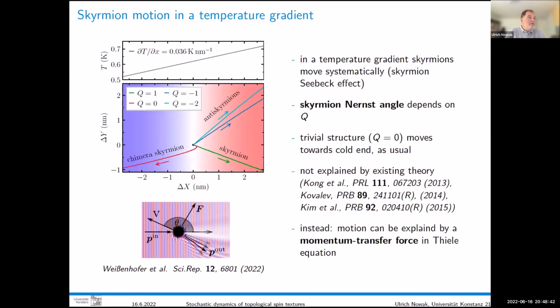The last slide I wanted to show regarding results is now what happens in a temperature gradient. So I showed already, okay, at finite temperatures, skyrmions, they move, they have Brownian motion, they can be described as quasi particles. What about in a temperature gradient? What this graph here shows is the trajectories of skyrmions with different topological charges. We simulate them in a temperature gradient. So in our simulation, this gradient is very large because we have small skyrmions and small system sizes. Anyway, so to the right is hot, to the left is cooler. And now you see with different topological charges, you get completely different trajectories.